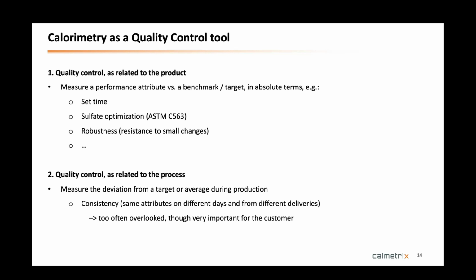So where you have an absolute performance target for the product, such as setting time. You need the product to always reach a certain setting time. So you have a concrete mix and you want to get to a target set time, and you test against that. So you could do a set time test with a Proctor needle, like ASTM C403 type, or you can use a calorimeter, or you use some tool to test a performance metric for a specific parameter.